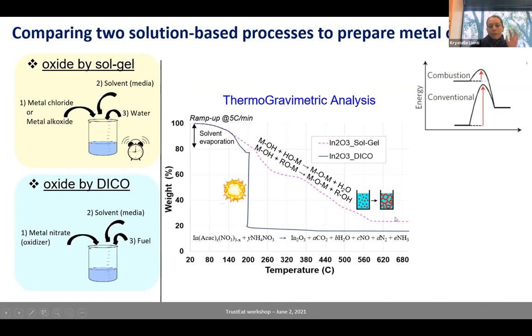Regarding the DICO process, as you can see, when we reach about 200 degrees Celsius, we have ignition, combustion, and all the weight loss is happening all at once. And then as we keep increasing the temperature, nothing happens anymore, indicating that already by 200 degrees Celsius, we have achieved our fully condensed oxide network.